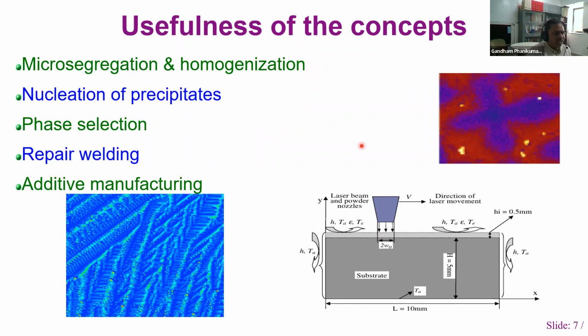So one of the things that we need to understand is microsegregation and homogenization. That is, how do the elements segregate as the solidification is happening during the additive manufacturing? And then how do we remove those microsegregations by giving a homogenization heat treatment, that is holding the material at a high temperature so that the ups and downs in the compositions are flattened out. That's what is called homogenization. So we have to understand that very well, because if you don't do it carefully, you may have cracks. Okay, and we will talk about that.